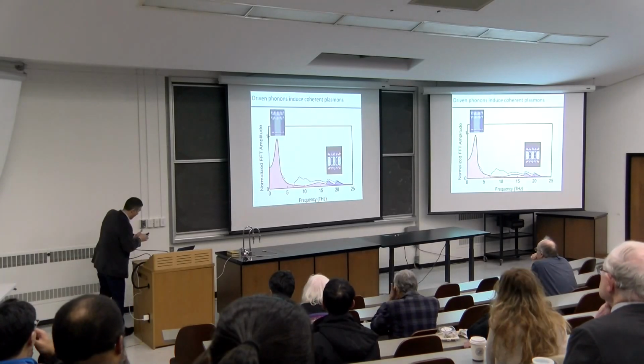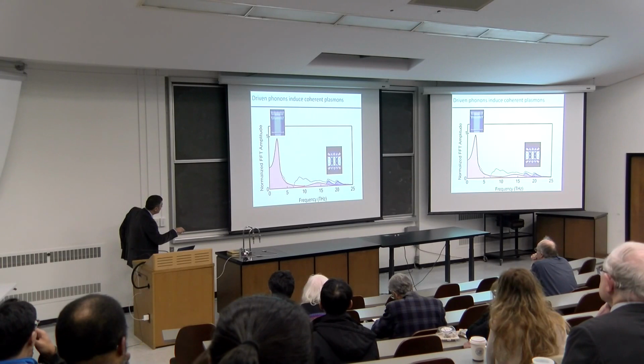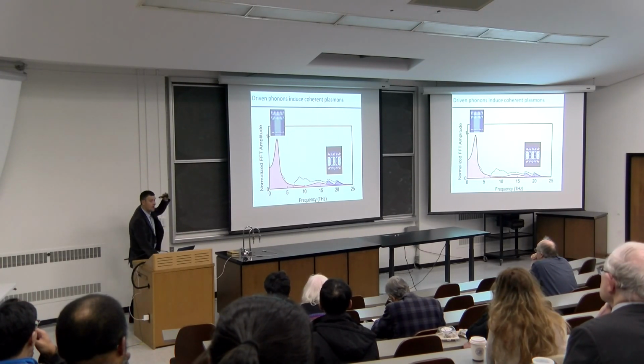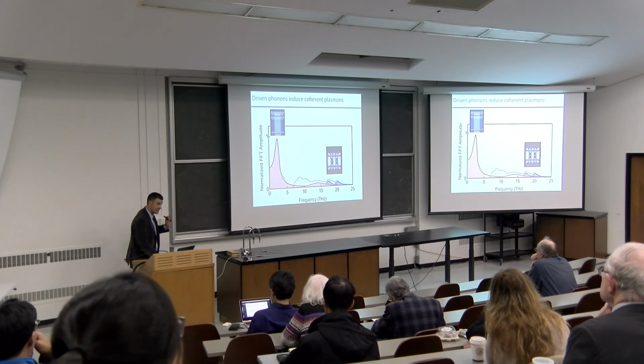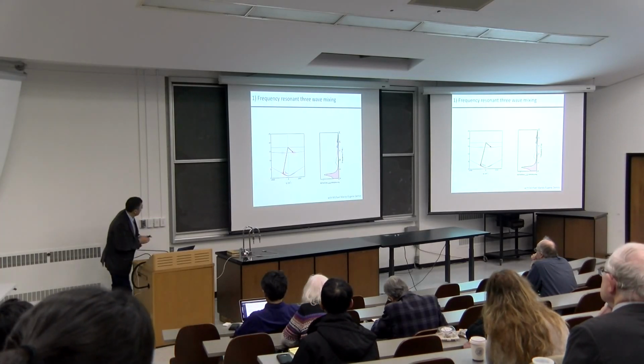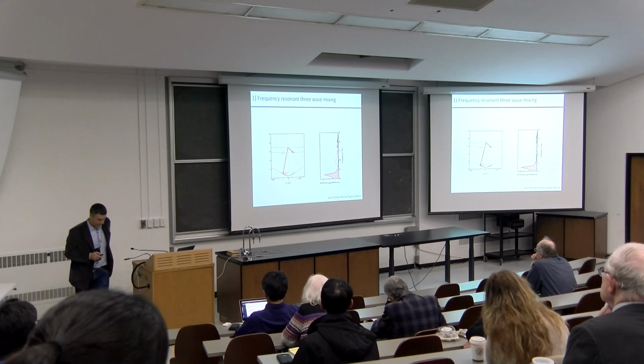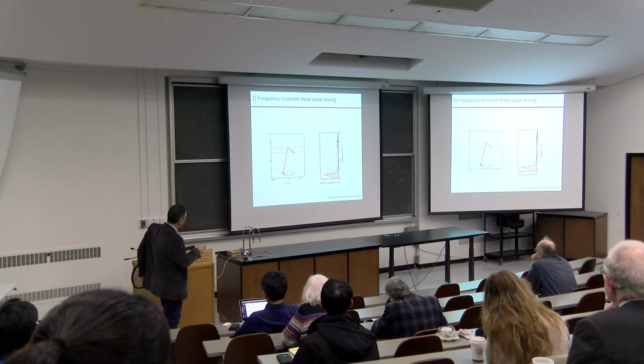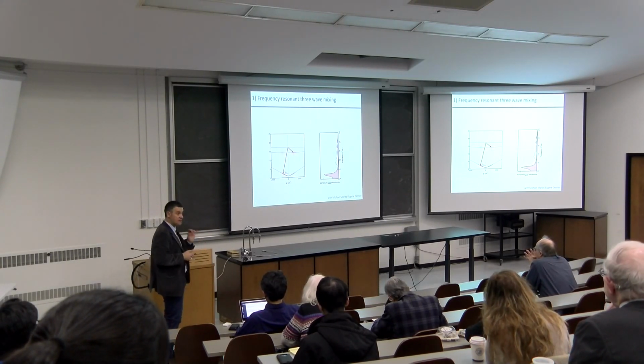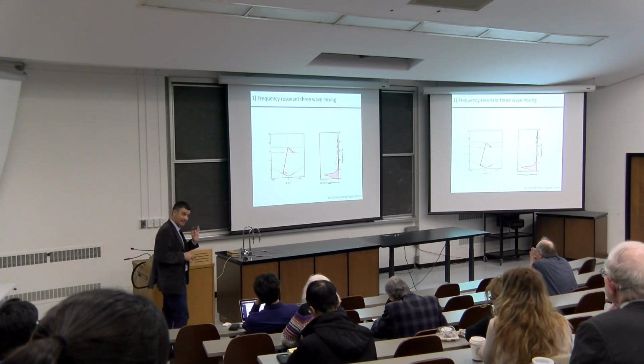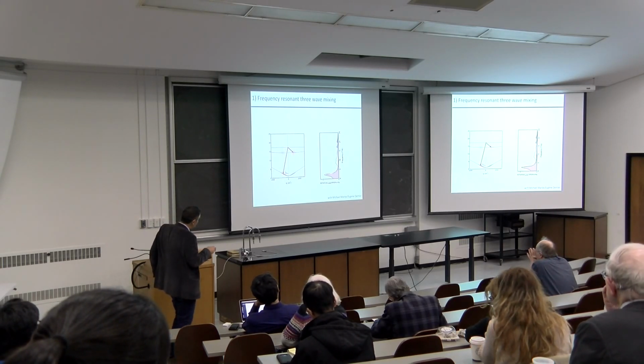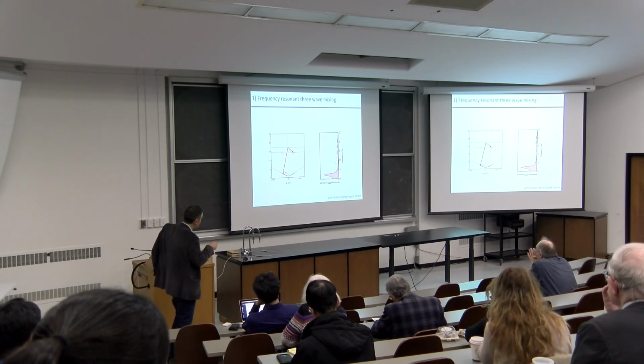And so basically what I have is that pumping a phonon here generates these interlayer tunneling currents that oscillate backwards and forwards in the superconducting state. So what I know is that, A, the prediction of the sum frequency matching is correct, and also because I know the dispersion of these modes, or at least I can calculate it. This is a solution of the equations of motion.